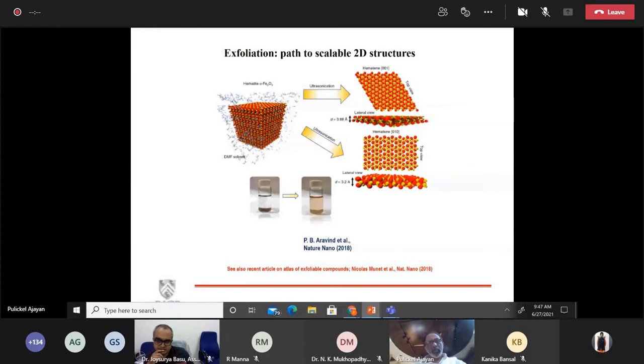I already mentioned that the graphene layers were made by a simple physical Scotch tape peeling technique in the beginning, and then later using exfoliation. Now, exfoliation has become quite a powerful technique to extract layers from different layered materials, even non-layered materials. If you can provide enough energy, you can cleave these different materials along different crystallographic planes. And again, getting to super thin layers could change the overall behavior of these systems. Here is an example of an iron oxide which has been cleaved, and when you've reached very, very thin layers, you can get some new emerging properties like magnetism and so on.